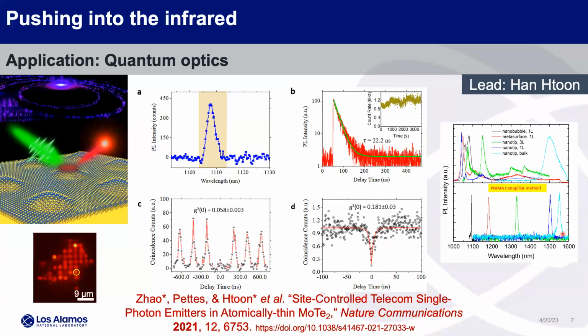The polarization that comes out of these things is always going to prefer one particular orientation. So you'll get what's called subband splitting if you looked at this at higher spectral resolution. But you can see the HBT dip here. It's even lower than what we did before. That's because the separation from band edge to defect is higher. So you're getting very good quality single photon emission. Basically put 1 minus this value, and that's your degree of single photon purity.